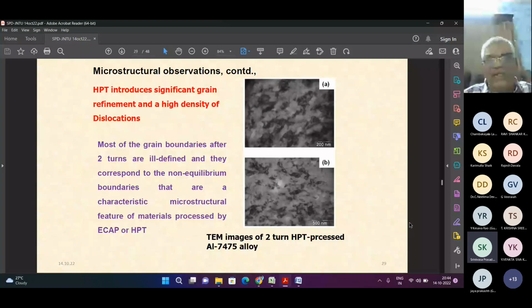And continuation of this one, only on high pressure torsion, of how it is influencing the microstructure. You can see that a grain refinement has happened, and a high density of dislocations. If you see image A, a high density of dislocations can be observed. And in the bottom figure, when you are observing these, most of the grain boundaries after two turns are ill-defined, and they correspond to the non-equilibrium grain boundaries.